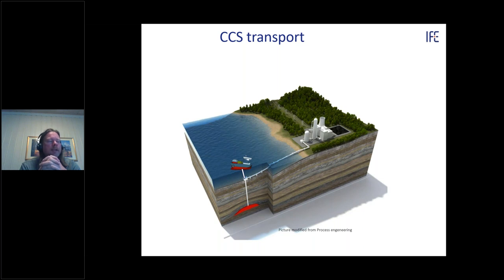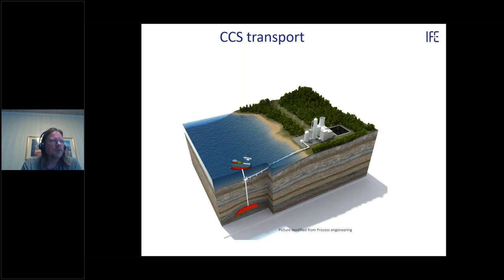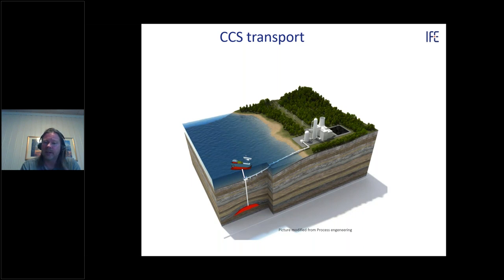As a corrosion scientist, we have two questions to answer: what material can be used, and what is the corrosion contribution for the thickness of the pipe or ship. For CCS, CAPEX governed the material choice — we had to keep costs low, so it was said quite early that carbon steel has to be used. That leaves one question: what is the corrosion contribution, how many millimeters do we need to add to the pipe to maintain pressure integrity?